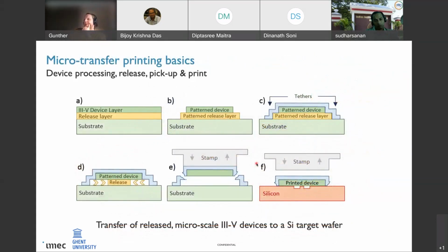Now, how does this microtransfer printing process work? Well, if you look at the III-V source wafer, it's not so different from the classical III-V device fabrication. So what you start with is a III-V layer stack: substrate and then an epitaxial layer stack. The only thing you need to do to enable the transfer printing is to include a release layer, a sacrificial layer in the III-V layer stack.